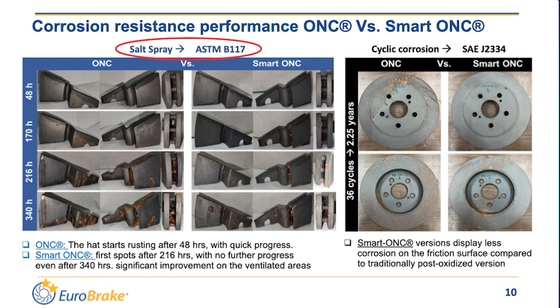The ASTM salt spray testing shows that the ONC starts corroding from the hat after 48 hours, and it quickly spreads. While for Smart ONC, we can see that the first spot appears after 216 hours, and it doesn't spread even after 340 hours. And we can also see that there is a significant improvement in the ventilated area.